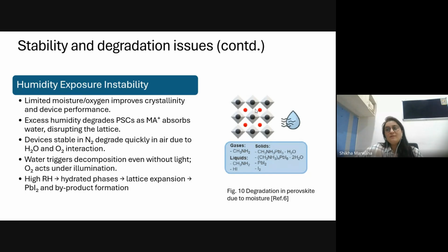If we have a limited amount of moisture, that can sometimes improve the crystallinity and also improve the device performance. But if the level of humidity keeps increasing, this excess humidity degrades the material as the methyl ammonium ion absorbs water. The water molecules start to interact with the methyl ammonium ion and disrupt its lattice, the internal structure of the methyl ammonium lead iodide.